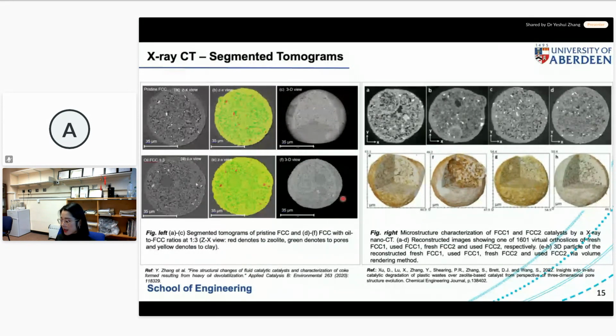This FCC catalyst, and other types of heterogeneous catalysts that we use, have a porous structure inside. So you still want to find out what happened inside, whether the porous structure has been damaged, or whether anything has gone inside these pores to change the porosity or surface area. That is one of the powerful functions of this X-ray nano-CT.